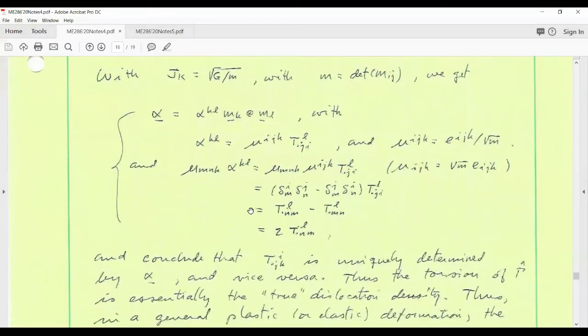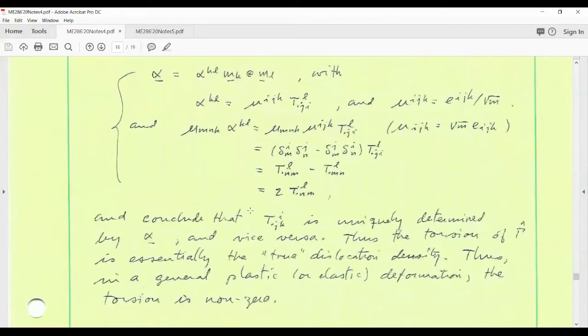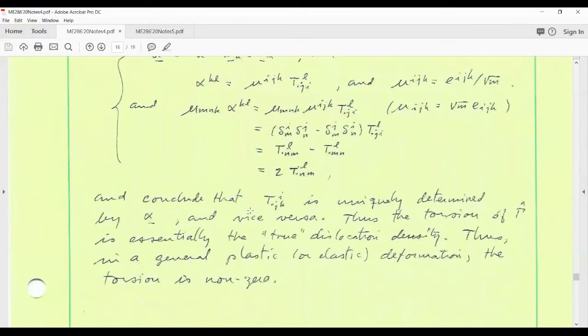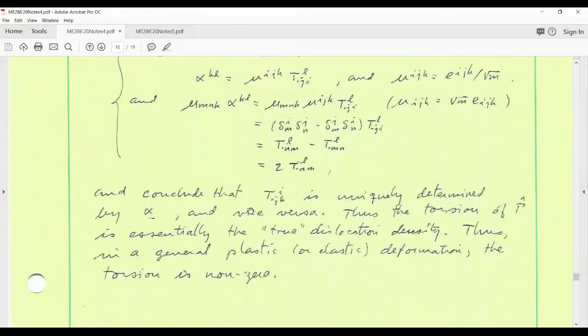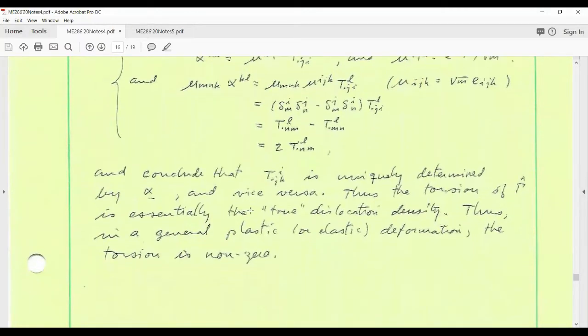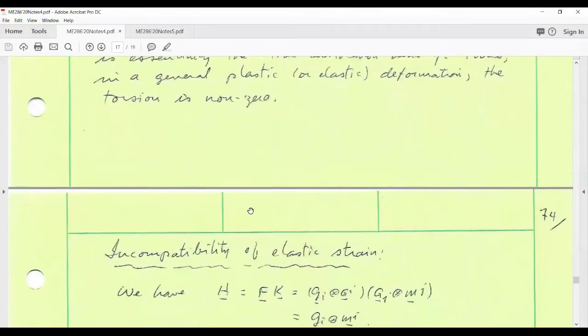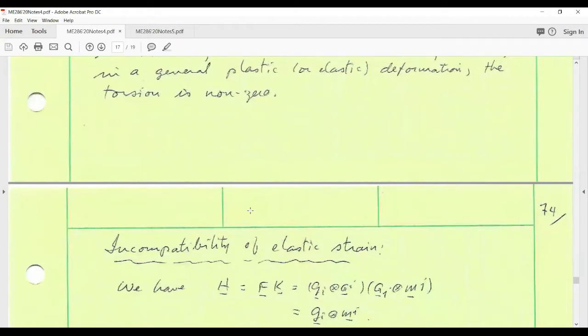You can see now why the geometry associated with plastic deformation is inherently non-Euclidean: it is associated with a set of connection symbols gamma-hat which are not symmetric in the lower subscripts, and the skew part of that object is the torsion, which is non-zero precisely because the plastic deformation is in general not a gradient. That property is fundamental to defining a Burgers vector associated with the dislocation distribution.